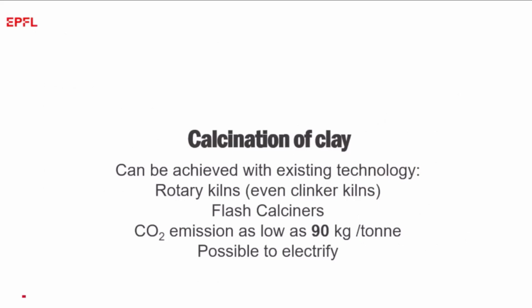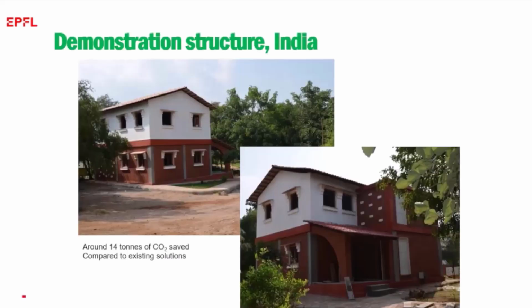So we can calcine it very simply with existing technologies. We can even do production in an existing clinker kiln. We did a trial where just 6 hours after stopping producing clinker, exactly the same kiln could produce calcined clay. Now, obviously, you don't want to switch production around, so if you want to produce calcined clay on a regular basis, it helps to have a specific kiln, but this can be a rotary kiln or a flash calciner.